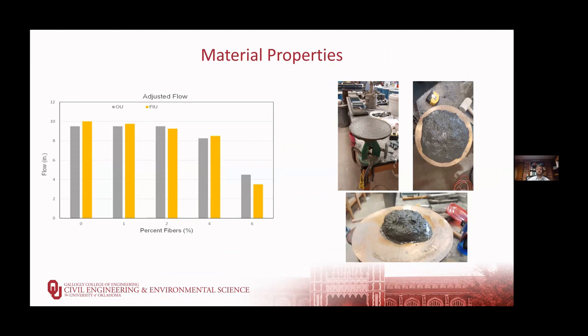We started by looking at the flow. We looked at it in terms of the percentage of steel fibers between 0% up to 6% steel fibers. We also looked at the difference between materials from OU, which is shown in gray on this graph, and materials from Florida, which is shown in yellow. We saw a decrease in flow once we got past about 2% steel fibers, even if we added additional high range water reducer. So we went from the picture on the top left, where we have a flow extending to the edges of our flow table, to where we go to 4% fibers on the right, where our flow is reduced, to where with 6% steel fibers, we basically have a fiber ball in the middle of our flow table.